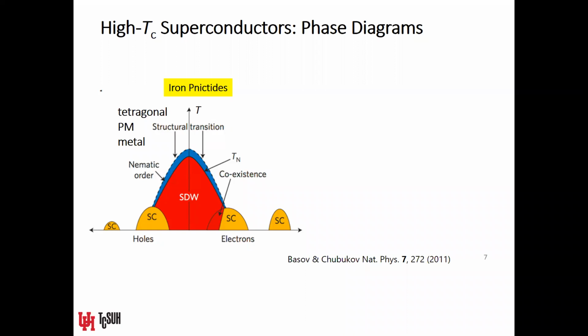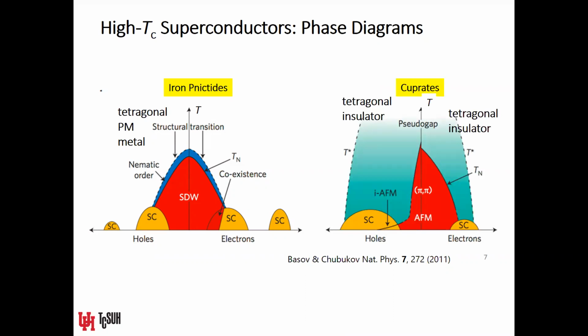As the temperature is driven down, you undergo these phase transitions that I previously mentioned, and with doping, you can alter those phase transitions, drive those to lower temperature, and you can push the system into the superconducting state. And you'll notice these two secondary domes of superconductivity, which give you a sense of the complexity of the phase diagrams. Now, there's the cuprate phase diagram, which is shown on the right, which has some general similarities to the iron pnictide phase diagram.